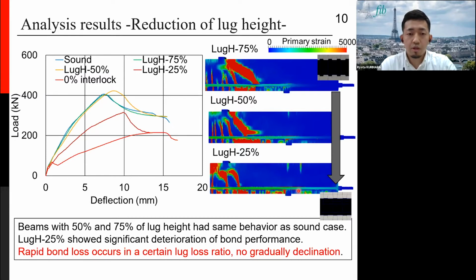In the 25% lug height case, the contact area between the lug of the rebar and the concrete in the pull-out direction is too small, as in this figure, so the bond force degraded. From this result, it is estimated that as corrosion progresses, at a certain lug loss ratio or surface roughness condition, rapid bond loss occurs. So the bond deterioration is not a gradual decline with corrosion progress.